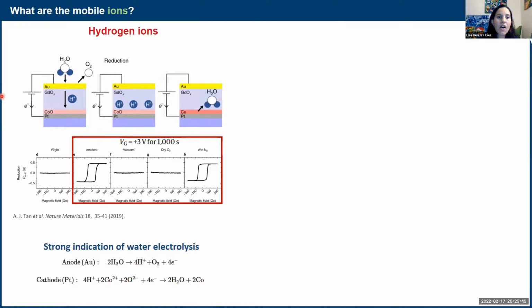In particular, they could see that this is really dependent on the water from the atmosphere. They could see that they really needed water to be decomposed on the surface of the top electrode, and then those ions would recombine and go into the layer as protons. So it was really important to acknowledge that the water from the atmosphere plays a huge role here, and it does as well in oxygen-driven mechanisms.